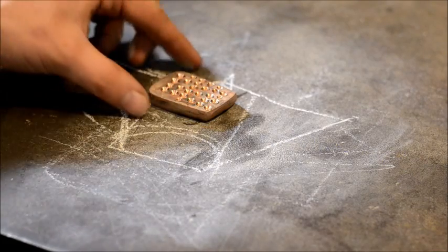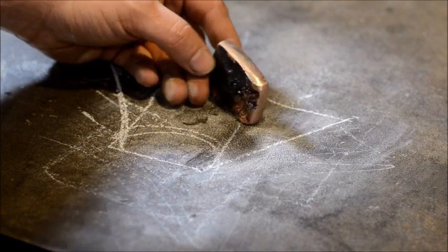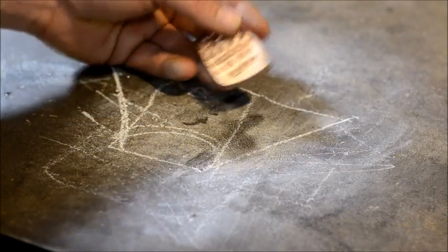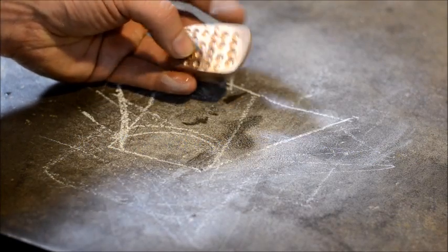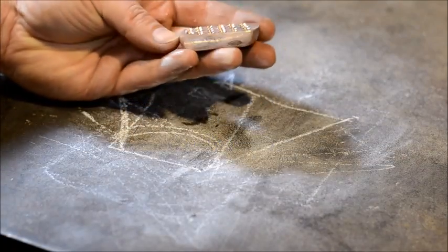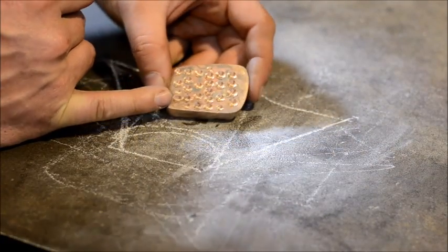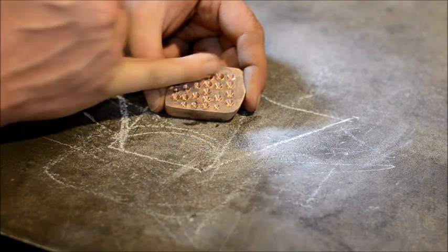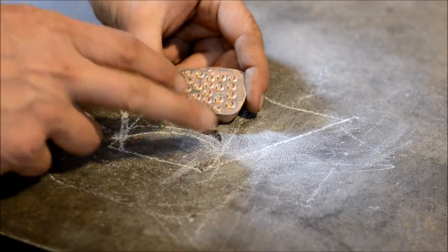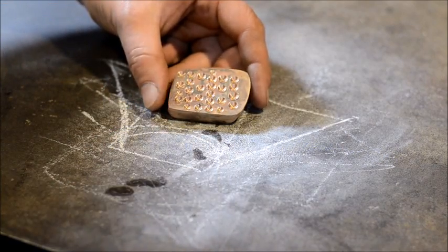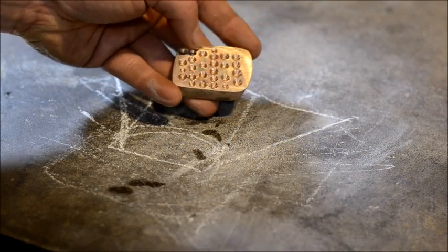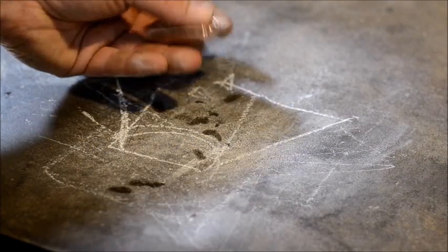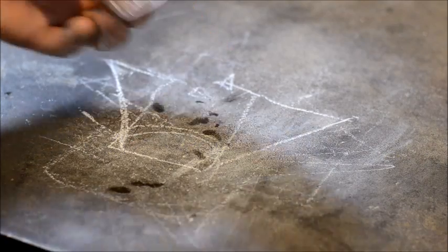So first step, that is done. I would also like to point out you want to clean up your billet after each go. And before you get to forge welding any other pieces together, always soak them out in acetone or denatured alcohol to take and clean it of any oils that you may have got from your hands and stuff. But for these purposes and the forging practices here, we're going to go ahead and get this billet nice and hot up to a nice forging temperature, and then we're going to start spreading this out. And I'll show you guys how that looks. We'll get this all spread out and then I'll clean it up and I'll show you what that came out to and what it looks like. And so this way you guys can get an idea of what that pattern produces. And then we'll be ready to move on to part four, which will be taking and patina-ing it and etching.